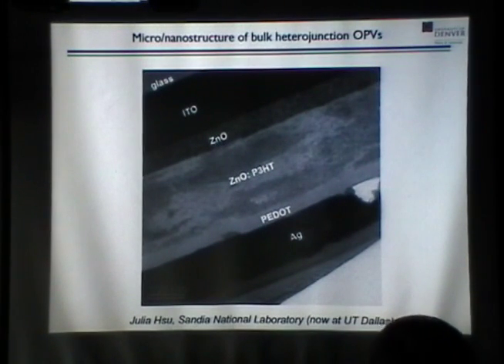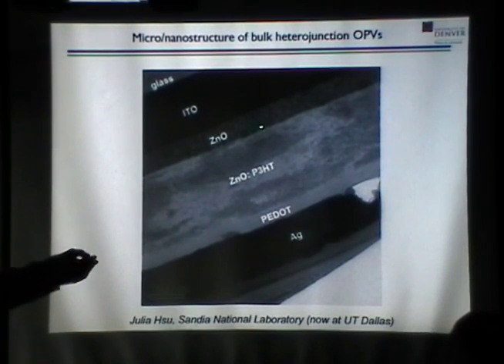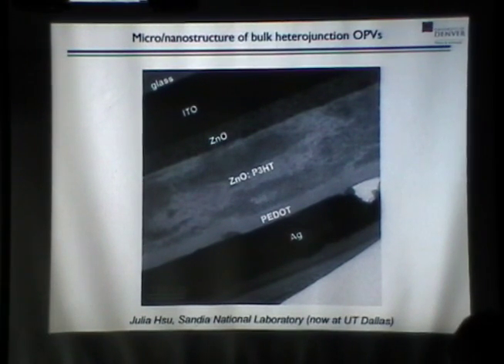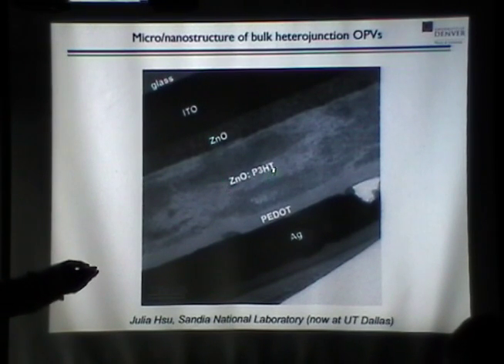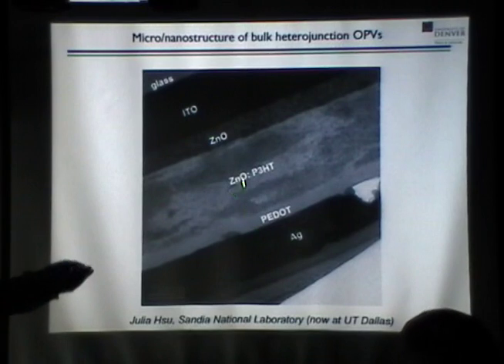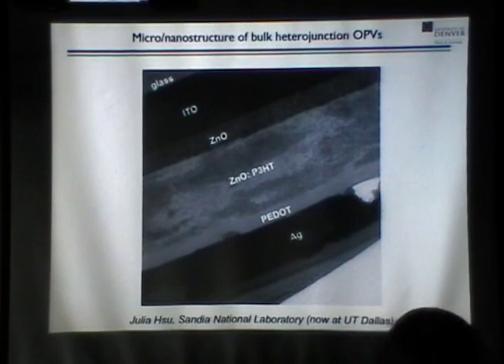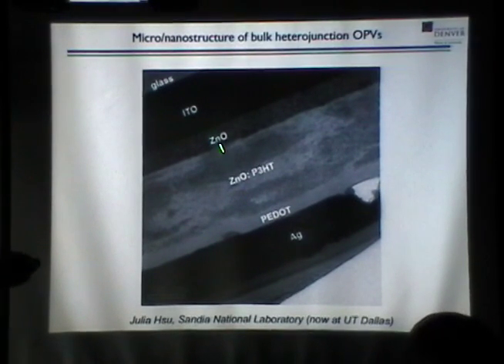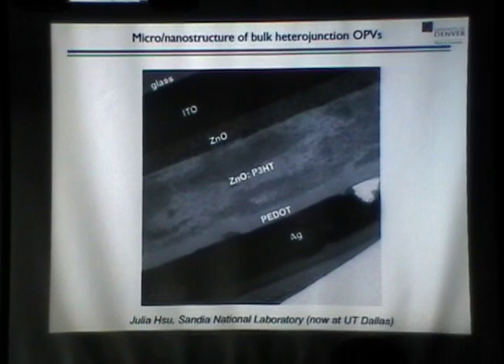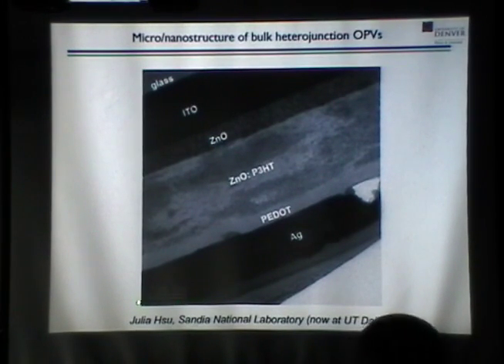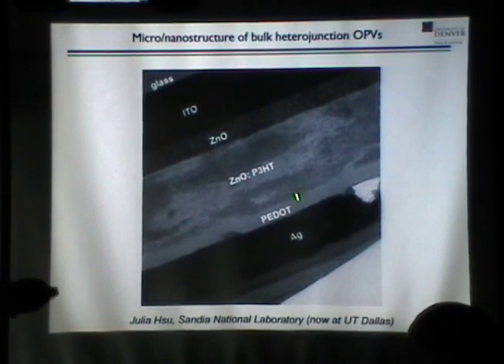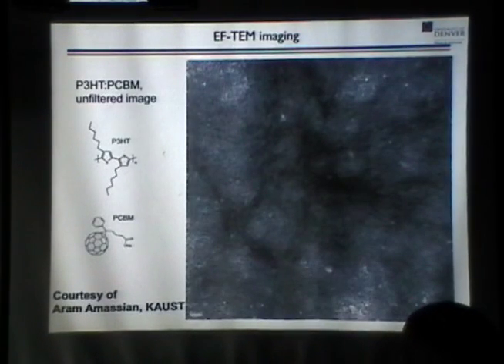First thing you notice is that it's not this perfect uniform mixture that I showed in the cartoon, that there's a lot of heterogeneity in this structure. So the ratio of the blending between, in this case, the zinc oxide and the polymer can change throughout the depth of the film. So that's a problem, right? We would like that to be homogeneous and somehow optimal for charge transport. So that's one of the issues we'll have to overcome. Scale bar here is 100 nanometers, so this is about 250 nanometers thick.